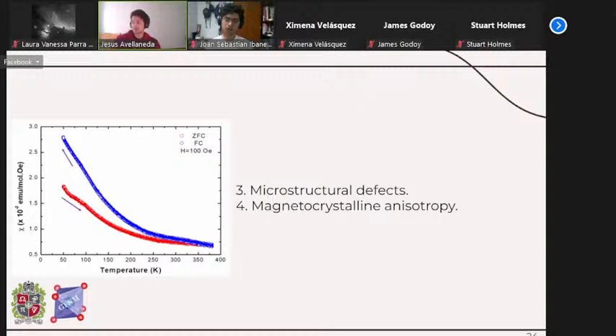And the last part is the magnetocrystalline anisotropy. Professor Ra suggested that we review literature on this topic because it seems at first glance that the system might have an easy magnetization axis, but these are studies that will be carried out later due to time constraints, basically, because as you know, if we want to rule out magnetocrystalline anisotropy, we should take measurements of the sample in different directions, something that is costly and really time intensive.